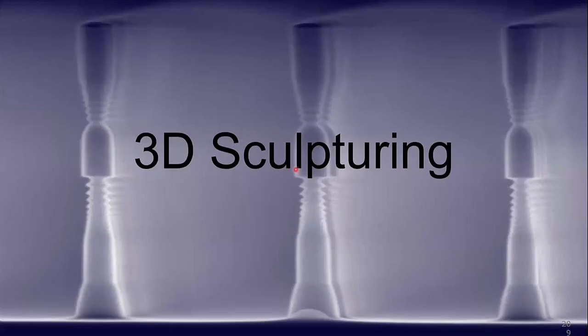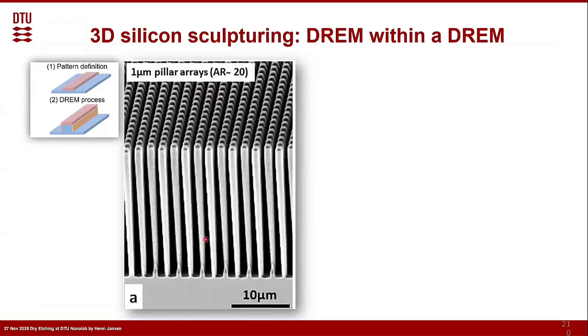While we are etching down in the switch mode, we are allowed to program, after a certain amount of scallops, maybe 10 small ones, that now we stop. I will make a slightly thicker passivation, and I'm going to undercut much more than previously. So all the time I have the same etch time in my Bosch process, but in one step I do it a little bit longer. After that, I again continue with the original one, and again, a long one. And that's what happens here.